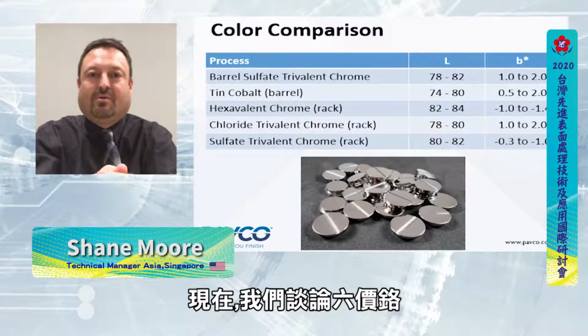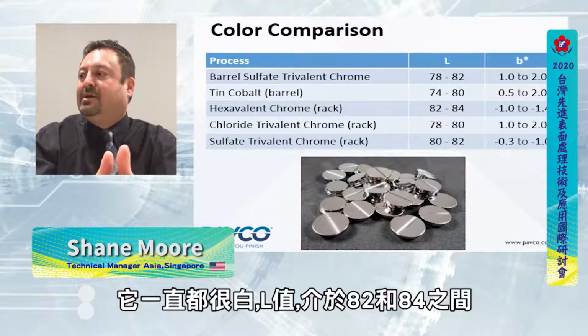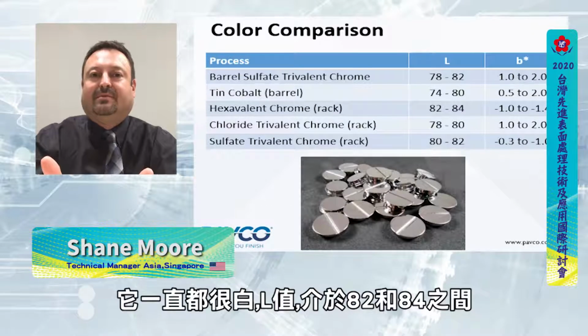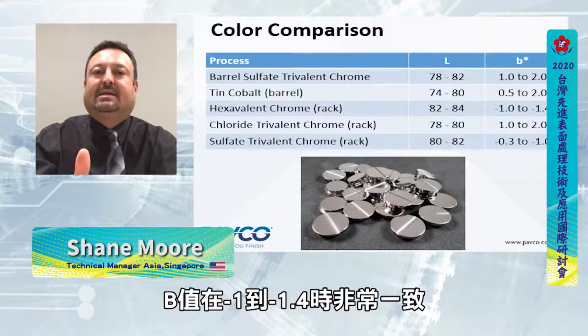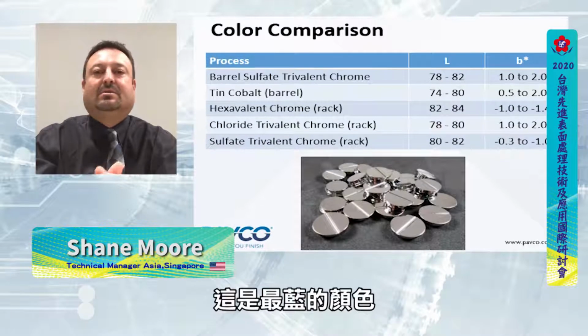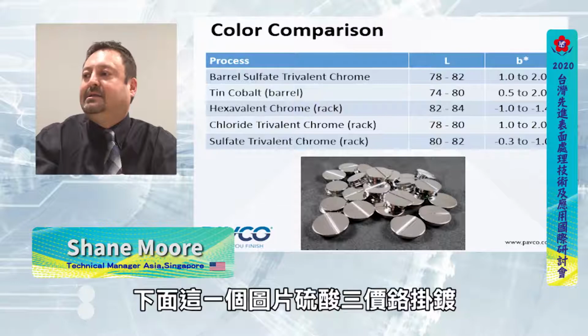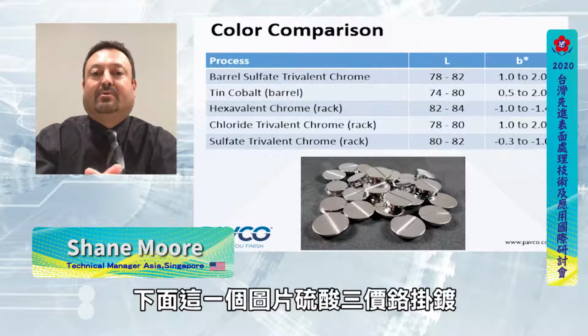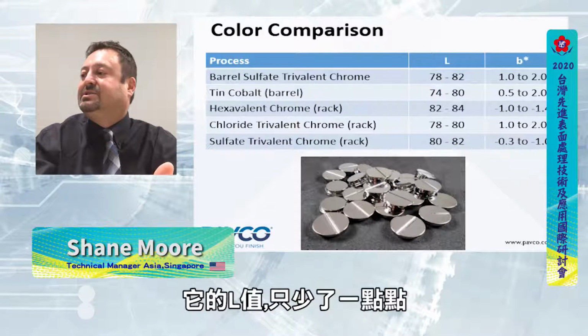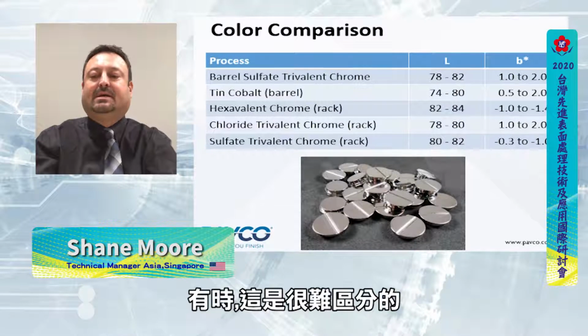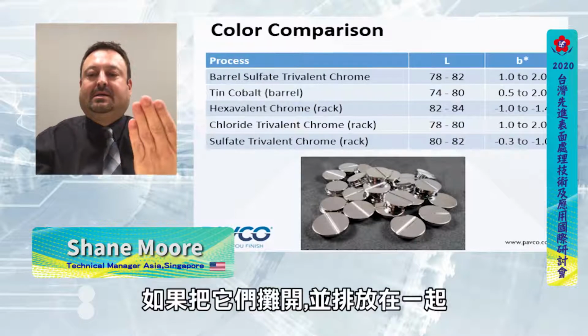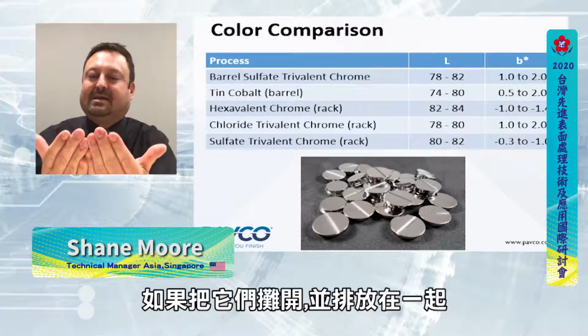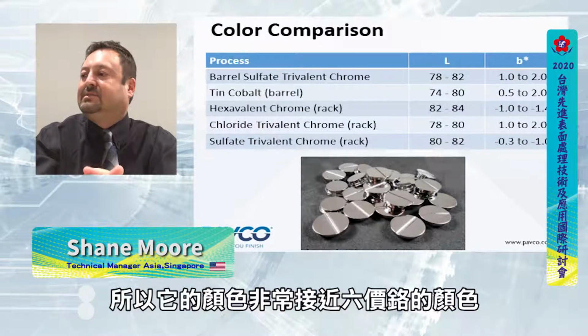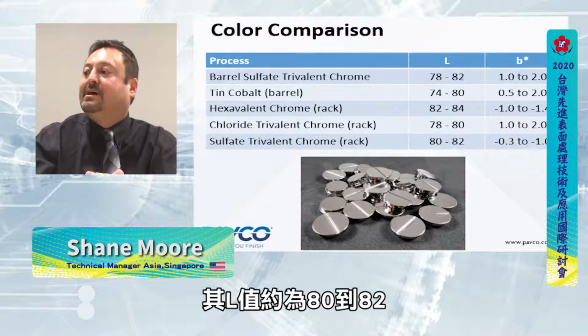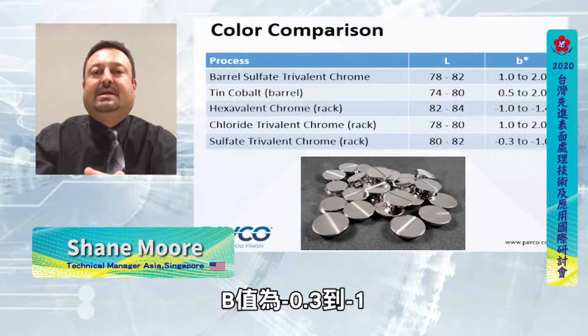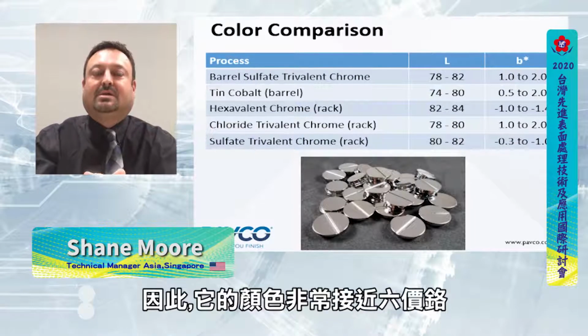So when we're talking about hexavalent chromium, it's consistently an L value, how white it is, between 82 and 84. The B value is pretty consistent at -1 to -1.4. So this is going to be the bluest color. The next in line is the sulfate trivalent chromium in a rack. It's going to have an L value of just a couple of marks lower, and sometimes it's really hard to tell the difference if they're this far away, and then by the time you get them side by side, sometimes you can tell, sometimes you can't. So it's very close in color to the hexavalent chromium. Its L value is around 80 to 82, and B value -0.3 to -1. So it's really close in color to the hexavalent chromium.